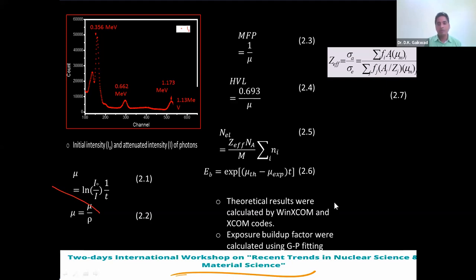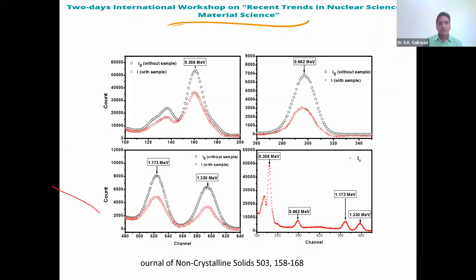Another tool is also available. We can even try an MCNP code, as the previous speaker has already discussed with us. This is one of our studies. We collected the spectra with and without glass. This is for 0.356 MeV, and these are for 0.662 MeV, different energies. The black bubble shows the measurement without the sample, and the red bubble shows it with the sample. With the sample we get very low counts, which means there is attenuation of the radiation by the glass.